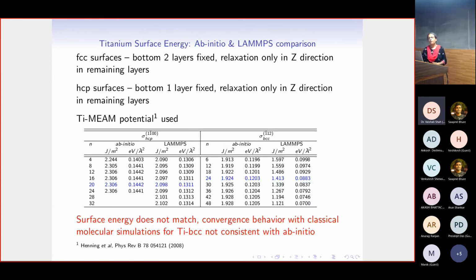Okay. So now we have a methodology, as I said. So now we simply do the surface energy calculation using first principles and the classical simulations. So for the classical simulations, we use the software LAMMPS, and for titanium, we have used the titanium MEAM potential that is developed by Henning et al. It's taken from the NIST library for EAM potentials.